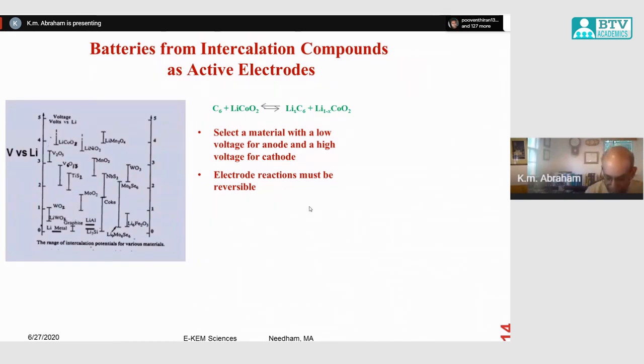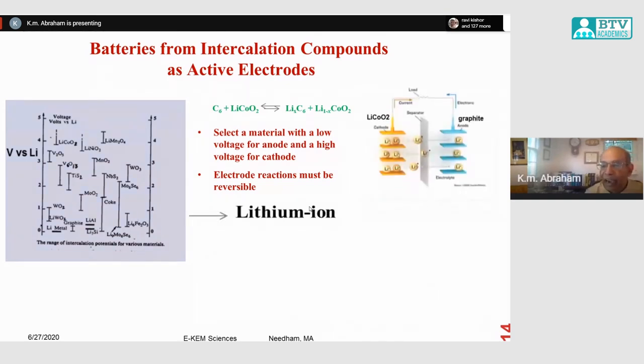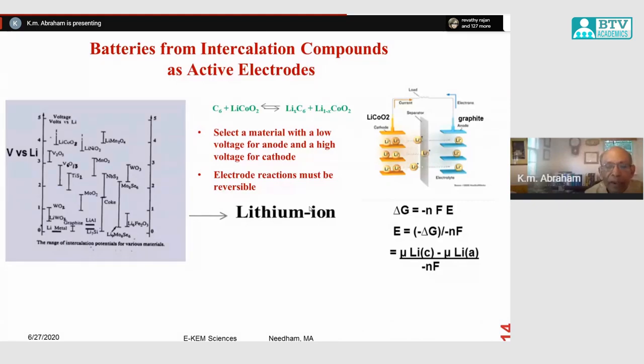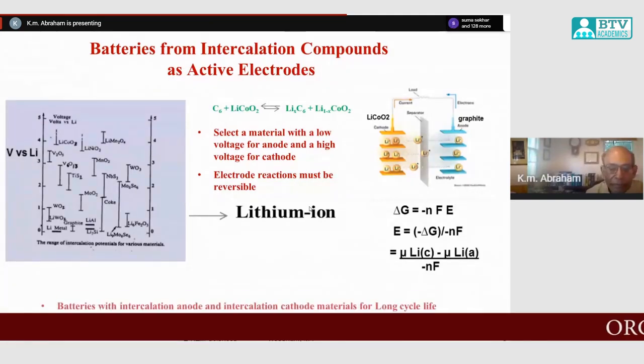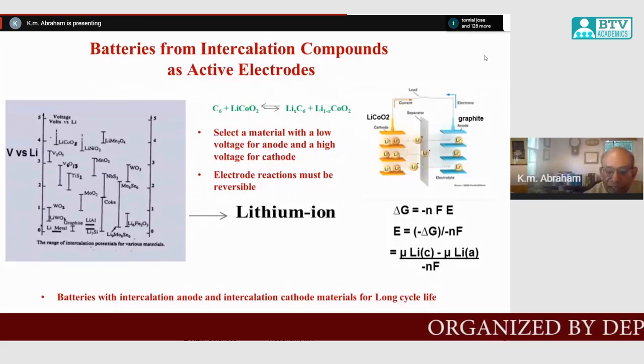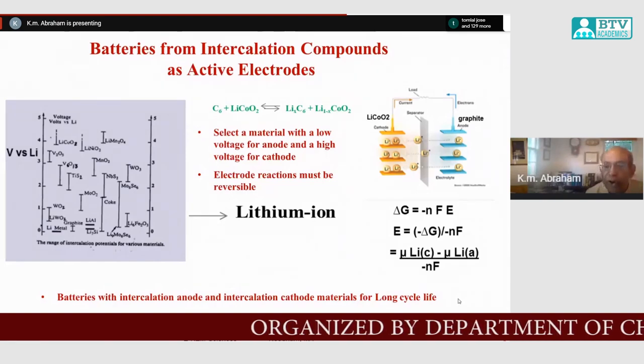So this is where the lithium-ion battery with graphite and lithium cobalt oxide was commercialized by Sony in 1990. The original lithium anode battery moved on to a lithium-ion battery where the negative electrode lithium metal was replaced by graphite, and the positive electrode was a high voltage metal oxide, lithium cobalt oxide. Batteries with intercalation anode and intercalation cathode materials give long cycle life.